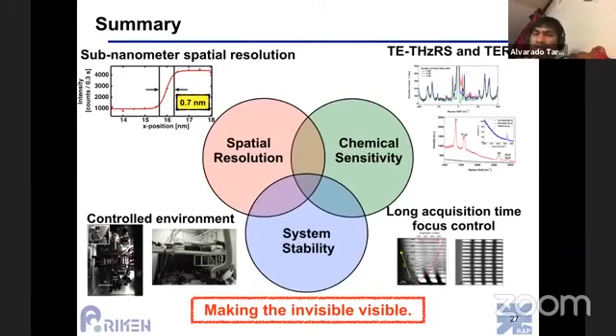So for those kinds of experiments, we still have to do a power Raman shift calibration to make sure that the Raman shift is still constant at a certain power. But once it starts shifting because of higher power, that's when we say, okay, this power is not good. So that heating caused by the tip is also not good for the experiment. So yes, I hope that answers your question.